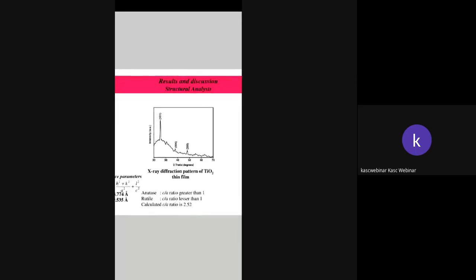And going to the structural property analysis, the prepared thin films are then subjected to analysis. First, we have to confirm whether the prepared films are of anatase phase or rutile or brookite. For that, we have undergone X-ray diffraction analysis. From this, we have compared the obtained graph with the standard JCPDS card data, and we inferred that the prepared thin films are of anatase phase TiO2.